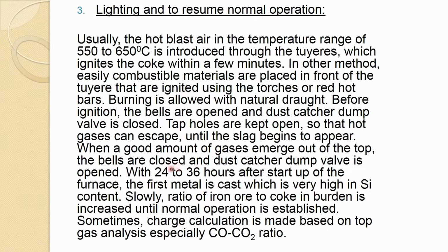So, now all the gas and dust catcher goes through that. Within 24 to 36 hours after startup of the furnace, the first metal is cast, which is very high in silicon content. Slowly the ratio of iron ore to coke in the burden is increased until normal operation is established.